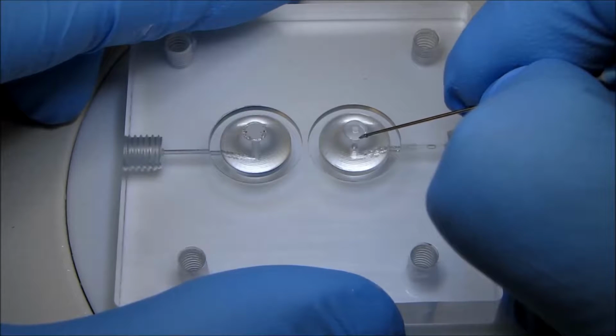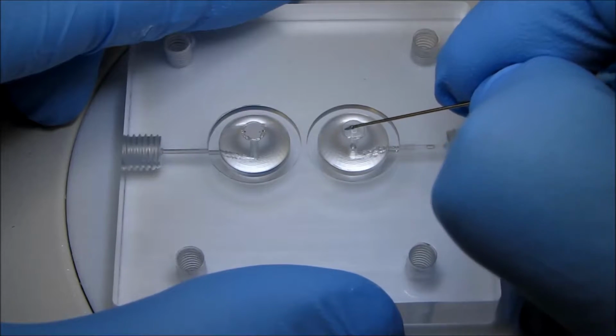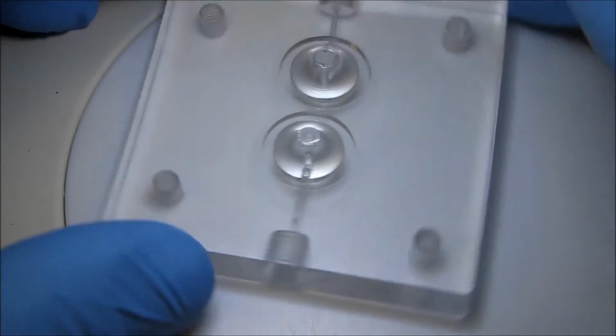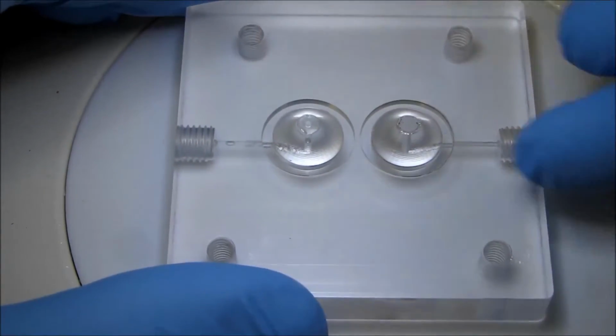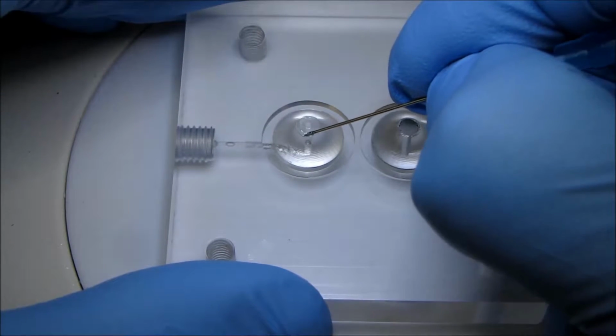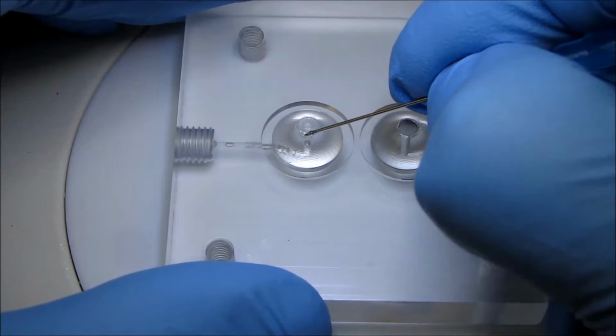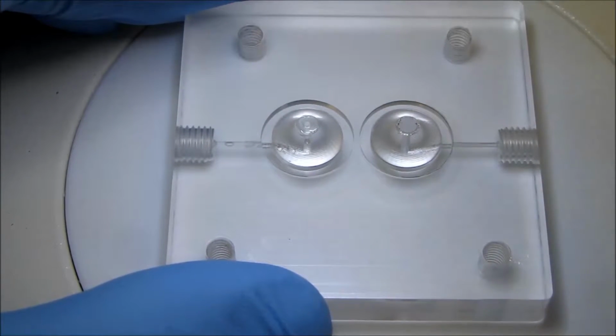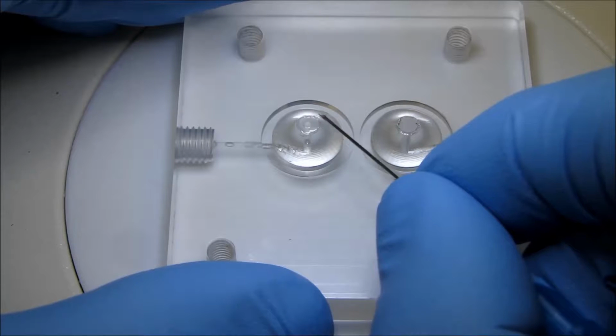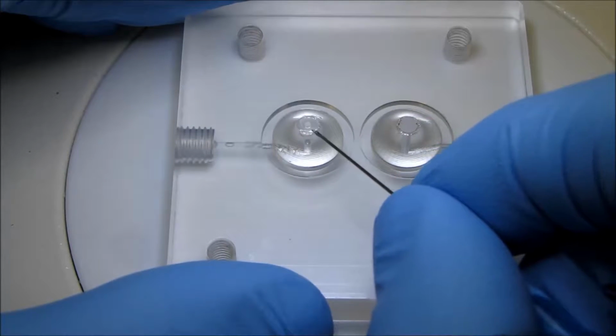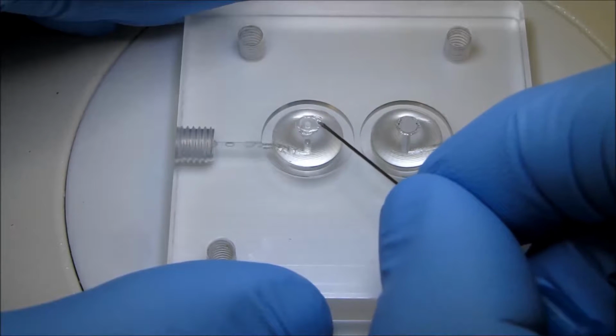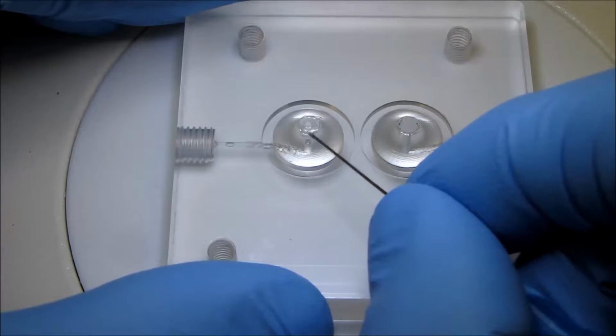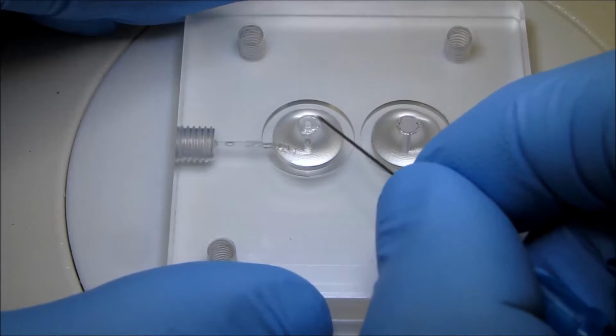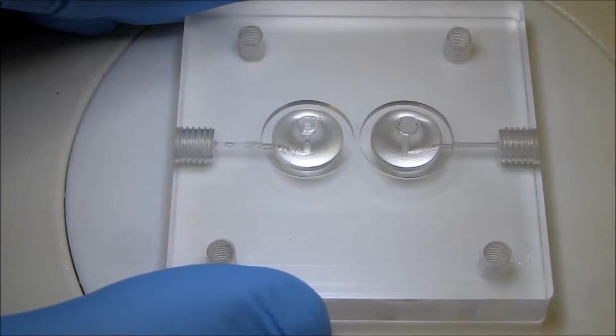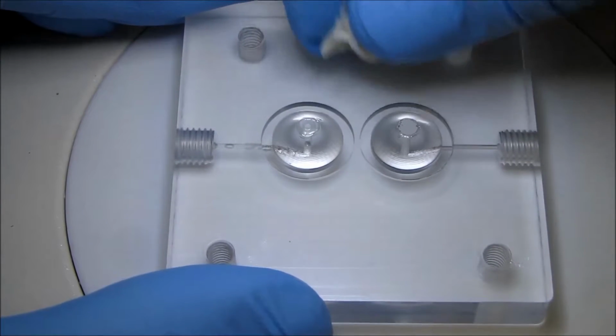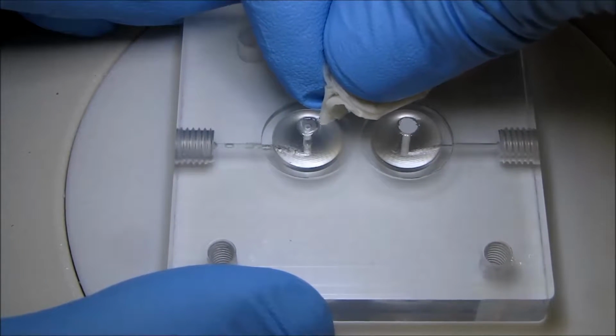Take special care to avoid getting glue in the hole in the center, as this will block transmission of the signal to the electrode. If glue gets into the center, flush it immediately with an alcohol-filled syringe. The best practice is to flush from the threaded end of the capillary and start over. You can use some alcohol to clean the sides of the cone if necessary. Just be careful not to interrupt your bead of glue.